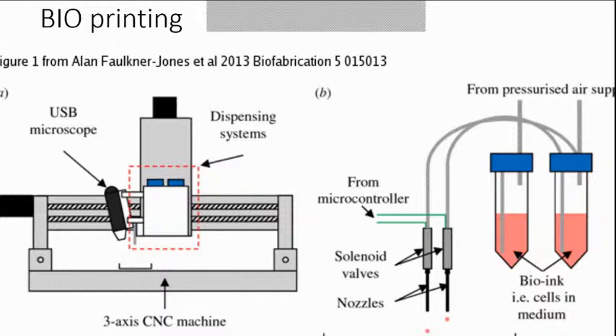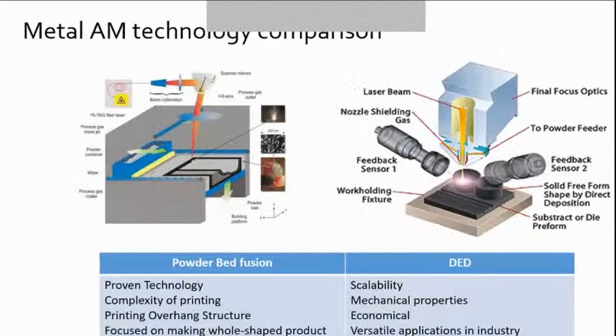In the case of metal powders, we need to do things slightly differently. You spread the powder, again one layer, depending on the thickness of the layer, and then using the same technology, in this case the laser, it sticks to the next layer and next layer and next layer, and thereby the part gets produced. This is called powder bed fusion. There is another technology called DED technology. In the case of DED technology, you don't spread the powder. You keep the powder in a hopper, and the powder comes in a calibrated manner, and the laser also comes.